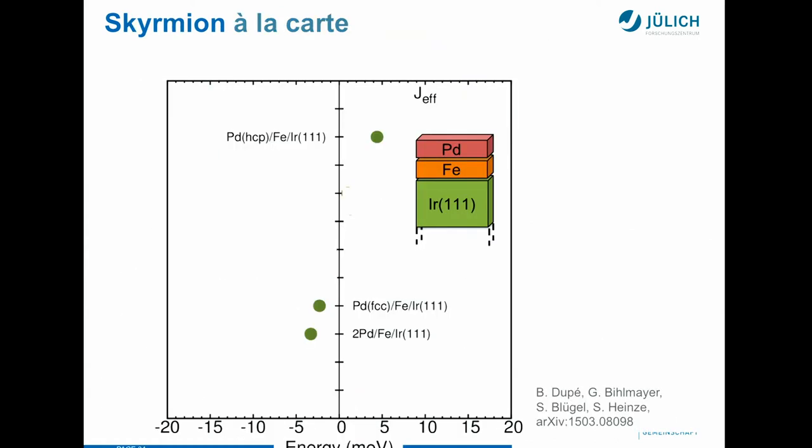And this we make use of. So we have one substrate, iridium, which has a strong spin-orbit interaction. So iron will polarize this iridium, it has broken inversion symmetry. This will produce the Dzyaloshinskii-Moriya interaction. Here, palladium has a large susceptibility. Iron will polarize palladium and manipulates the exchange interaction. And by varying these two interfaces, we can modify the exchange interactions.